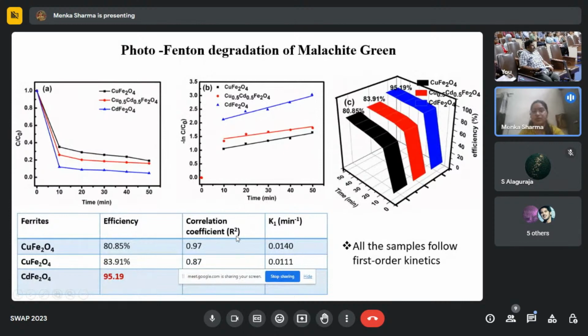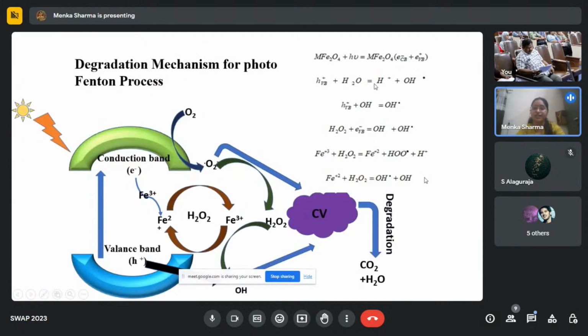For the degradation mechanism of the photo-Fenton process, we have used the photo-Fenton reagent to degrade our pollutant. When a ferrite surface is irradiated with visible light, electron and hole pairs are generated. If a hole further reacts with H2O, it will produce H+ ions and hydroxyl radicals. We are using H2O2 as a reagent, so H2O2 reacts with the electron and produces hydroxyl radicals that enhance the photocatalytic degradation efficiency. And Fe2+ ions will further react with H2O2 and again create hydroxyl radicals. So the hydroxyl radicals are created by three paths. That's why the degradation efficiency is enhanced in the case of the photo-Fenton reagent.